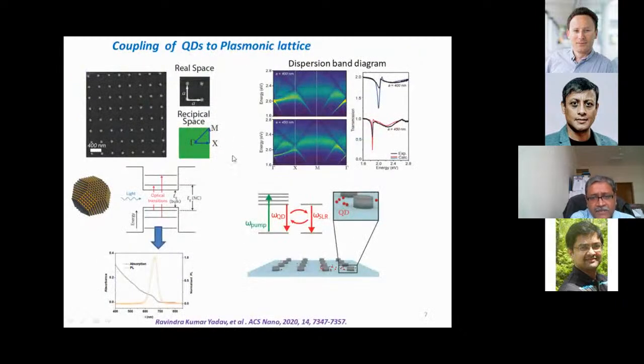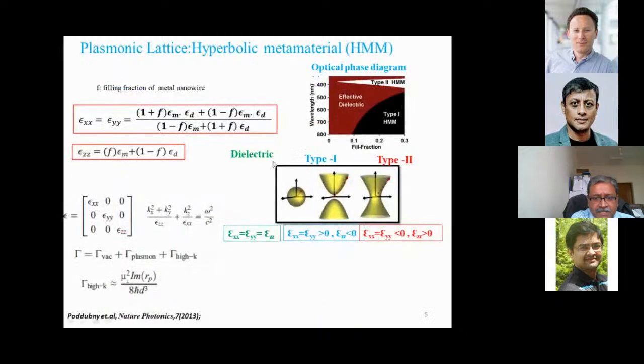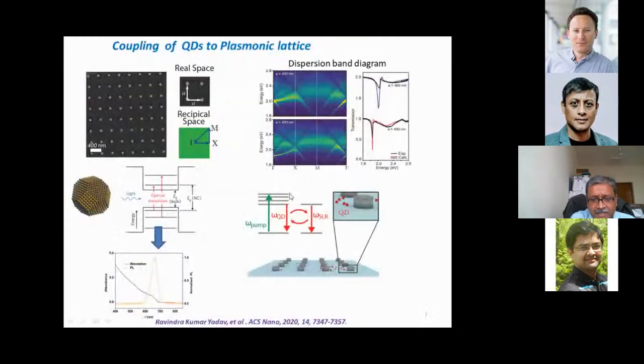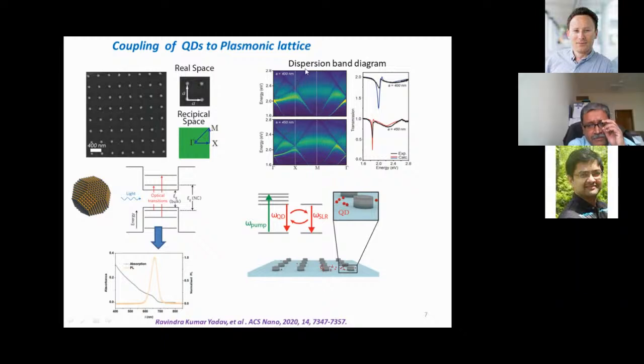What our interest is basically is to take one such array, and this is something which is fabricated in the group of Teri Odom at Northwestern. You can imagine that you can calculate a band diagram and a dispersion relation as well, and different size arrays indicated here will give you different dispersions. You can see the resonances here for different lattices. You can see the larger lattice spacing shifting the peak to lower energy.